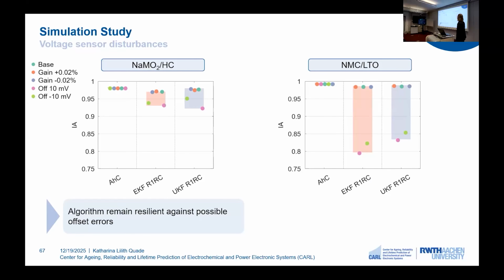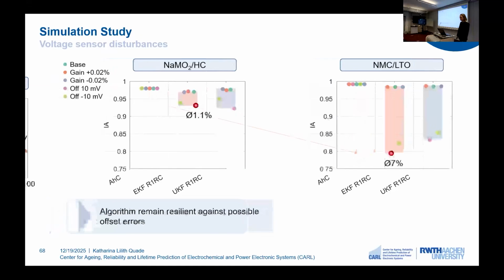Now let's compare this to our NMC-LTO cell. And let's focus on the model-based algorithms again. And we can see here that the same scenarios correspond to a significantly lower index of agreement value. And we can also quantify this with our framework. We can see that for the worst case in the EKF, we have a mean absolute error of 1.1%. And for the same scenario for the NMC-LTO cell, we have a mean absolute error of 7%. And this is definitely not acceptable, of course, for the application.